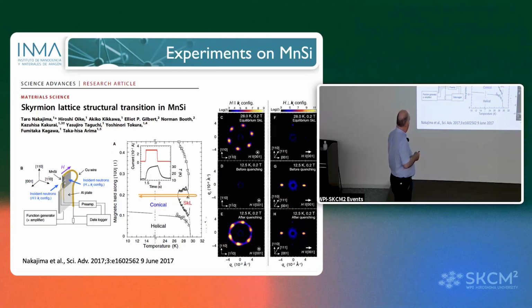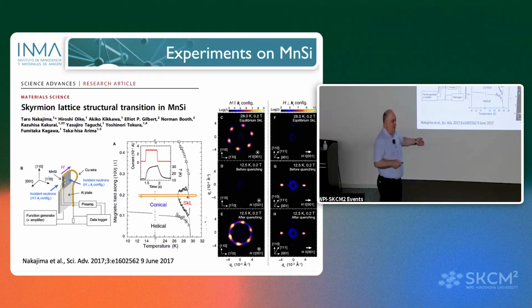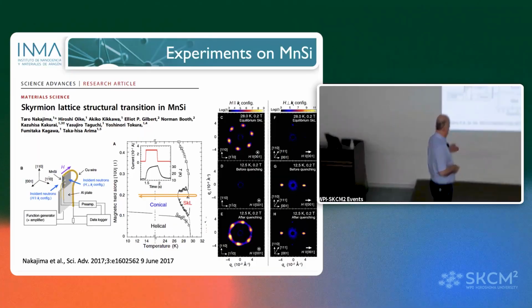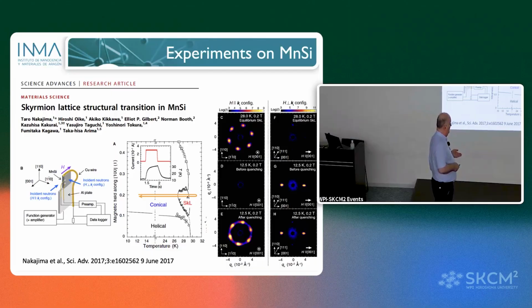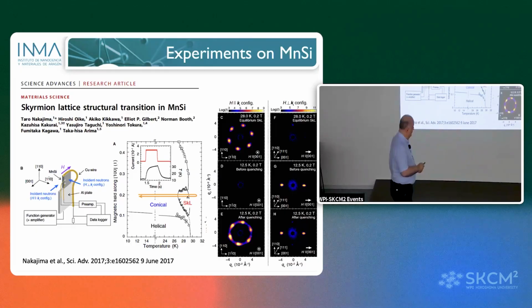And then they apply a pulse of current. They heat the sample very fast, and then they cool down. But they cool down passing through the skyrmion lattice, and they trap skyrmions at low temperature, and also helices. This is in very good agreement with our prediction, because here, in fact, the skyrmion is metastable at low temperature. If you wait, you will have only helices. This is in very good agreement with our prediction.